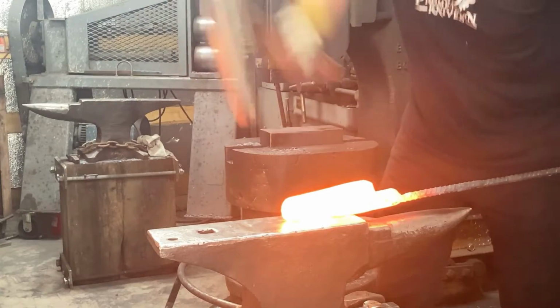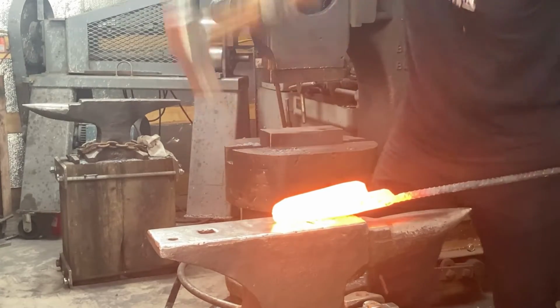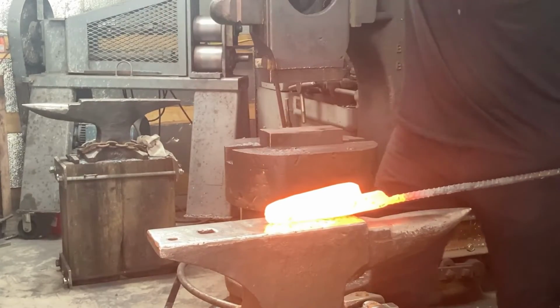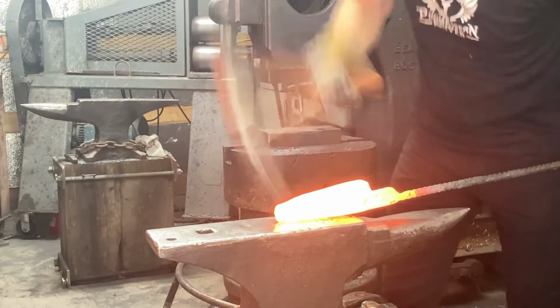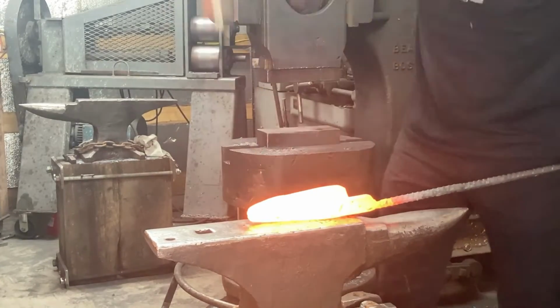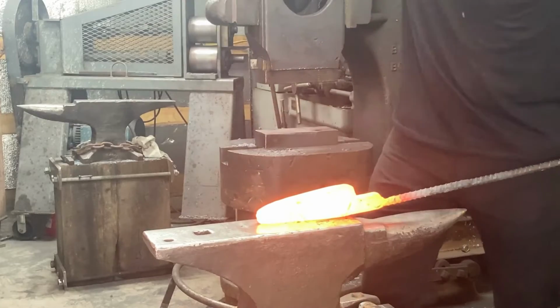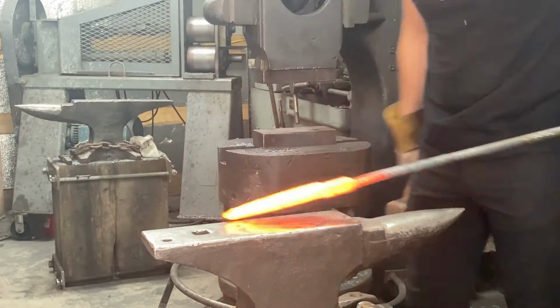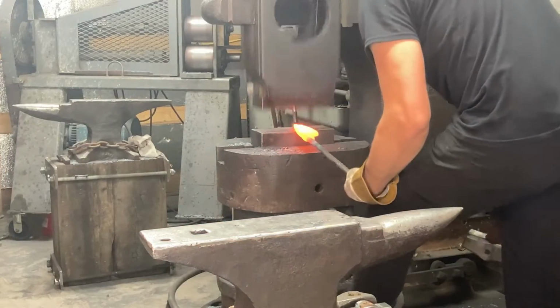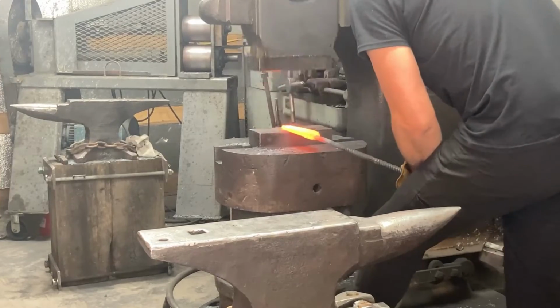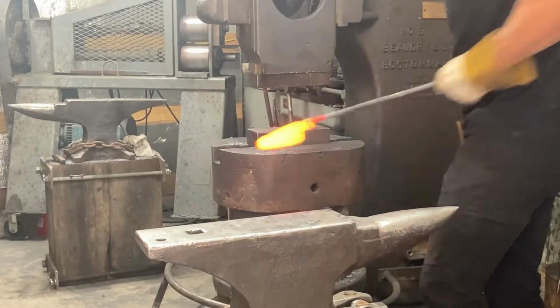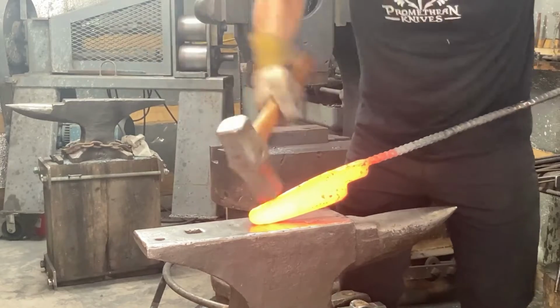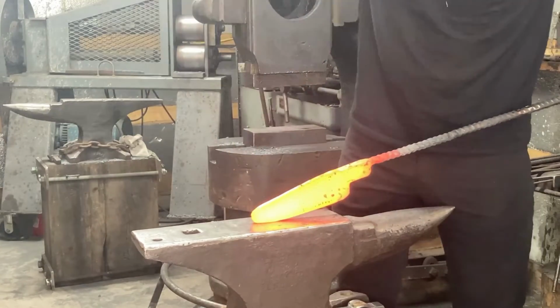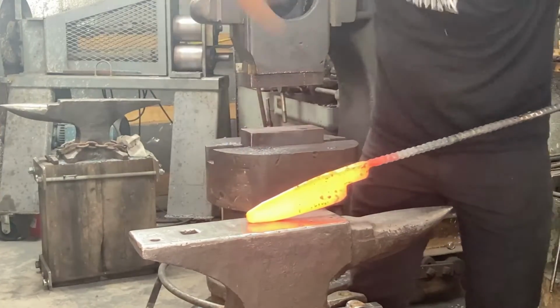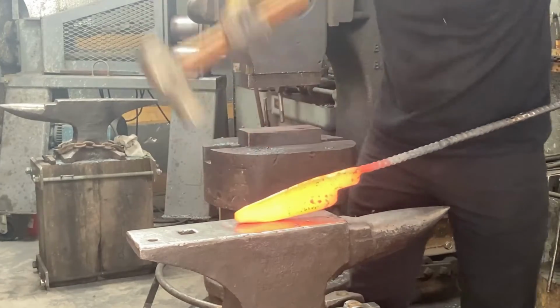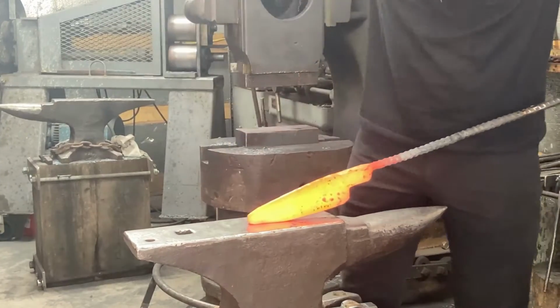Now we're starting some of the hand forging. Now that the billet thickness has gotten a little bit less, I've done a little bit of the heavy taper drawing work on the hammer. I'm using a 6.5 pound dog head hammer made by Ilya. This is a very nice hammer, perfect for this kind of work. You don't want to hammer fast with it, just accurate and hard. And it has the authority to continue knocking this tip shape in, even with that blade at 3/8 of an inch thick.